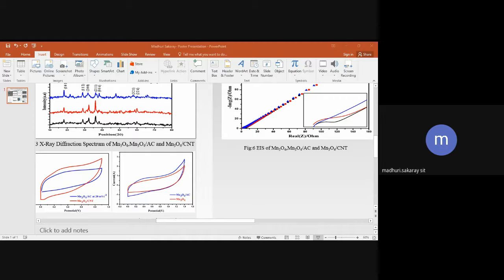The experimental procedure goes like this. Manganese acetate and citric acid in a 1 to 2 ratio were taken and stirred for half an hour, and simultaneously carbon nanotubes and activated carbon separately were dissolved in 30 ml of distilled water and sonicated for half an hour. These two were mixed, and pH was maintained at 7 by adding ammonia drop by drop, and this was stirred for 2 to 4 hours until the gel appeared. This gel was collected, dried at 100 degrees centigrade, and calcined at 400 degrees for 4 hours to remove the impurities.